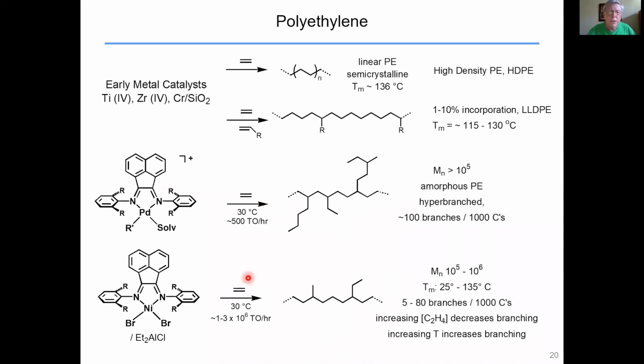In the case of the nickel, we've made well-defined catalysts, but an easy way into the systems is to simply take the nickel dibromide and activate it with diethyl aluminum chloride or other metal alkyl aluminum activators. These systems are extremely reactive. So they turn over about anywhere between 1 and 3 million turnovers per hour, as opposed to the palladium, which turns over very slowly at say 500 turnovers an hour.